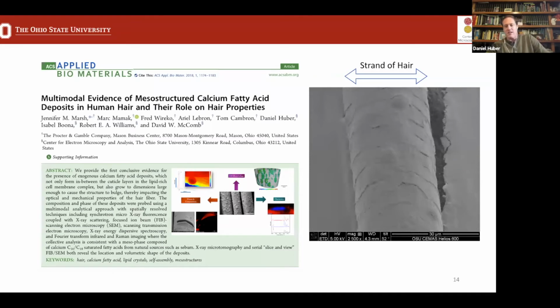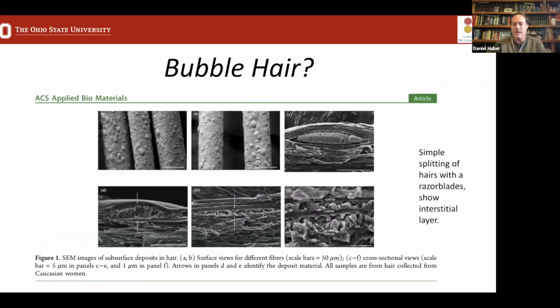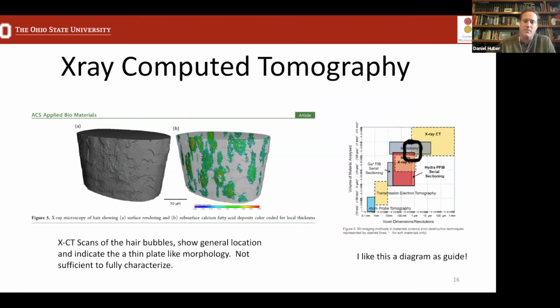Some of the initial things they had looked at were just taking these hairs and slicing them with a razor blade to expose the internal structure. You can see the cuticle layers, the cortex material, and these little bubbles existing interstitial to the cuticle layers. In other attempts, they've done X-ray microtomography to look at the distribution of the bubbles on the outside of the hair. They can see that the bubbles have a plate-like morphology, but we really couldn't see exactly what the internal structure was.